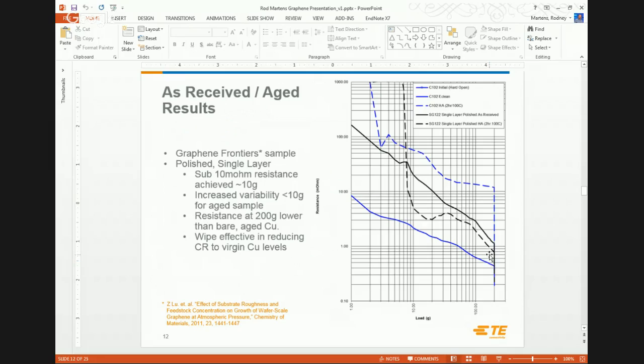But it's a few milliohms higher than the clean copper. But then we thermally age it at 2 hours at 100 C, and you can see that the results are fairly similar. They're a little bit off here because I'm plotting the median of 9 tests. So basically, we're not seeing a big impact of thermal aging here. It's again a preliminary study, but this is an initial data set.